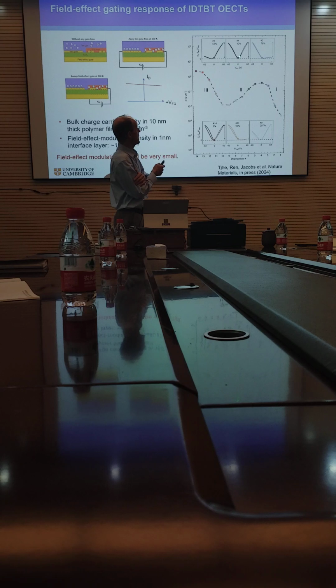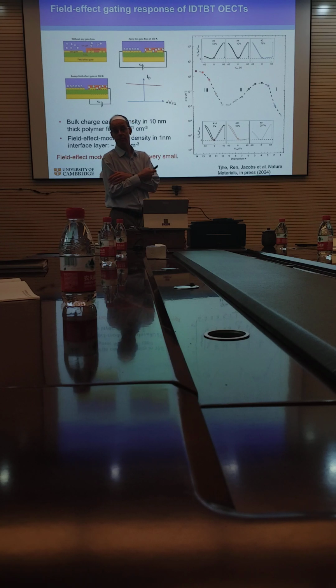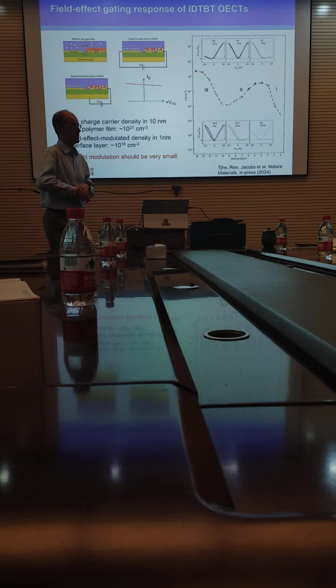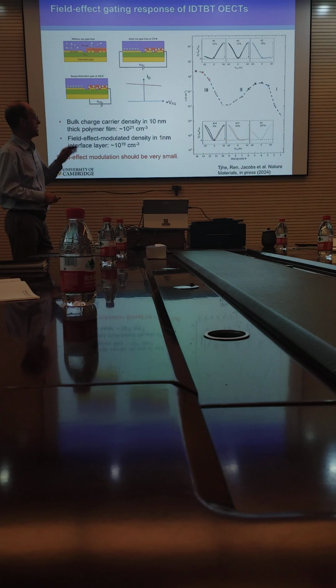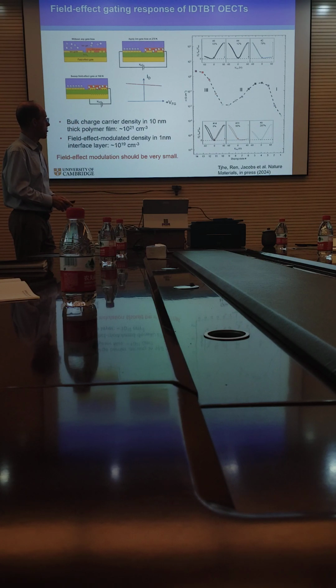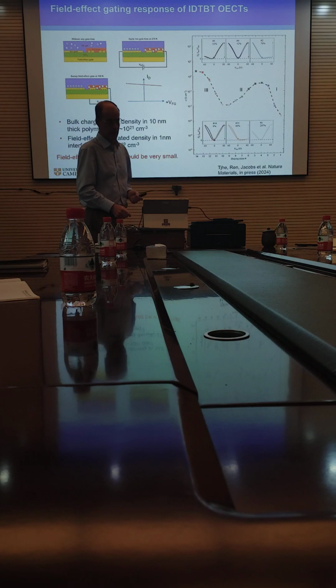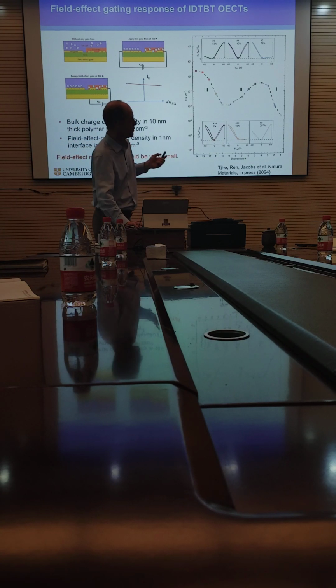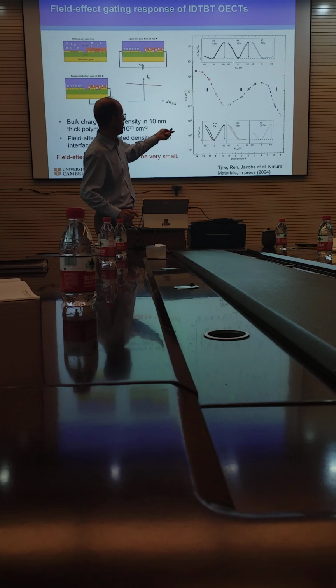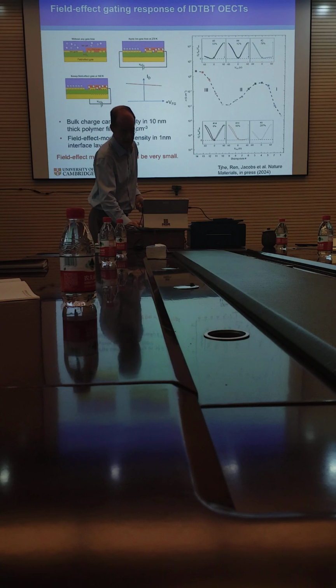But what we actually saw in the experiment is that in both directions the current increases. And not just by 1%, but by up to 12%. At other points, you can get similar current increases. In some cases, you get more than 100% increase in current. So completely unexpected, and it really puzzled us, we didn't understand what this was caused by. And I now want to explain to you briefly what we think is happening here, why we get this beautiful ambipolar response at this point, and the current increases by quite a bit more than we had expected.